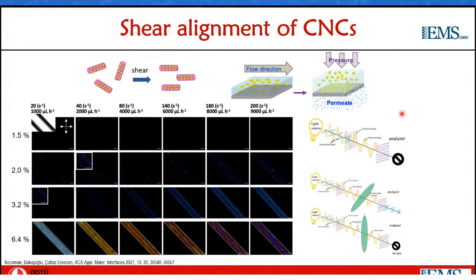So the first thing we wanted to see was under what conditions the nanocrystals would align. The tool we use here is polarized optical microscopy. When you have cross polarizers where the polarizing filter and the analyzer are at 90 degrees to one another, and when you have an isotropic sample, you have no light transmitted through your sample. On the other hand, when you have an anisotropic sample, such as cellulose nanocrystals in shear alignment, where the material is aligned at a certain direction, when this alignment is in the same direction as either the polarizer or the analyzer, you again see no light transmission through your sample. But when the alignment is different than either the polarizer or the analyzer, you start seeing some angle dependent light transmission. And this angle dependence is such that at 45 degrees, you would see the highest light that is transmitted.